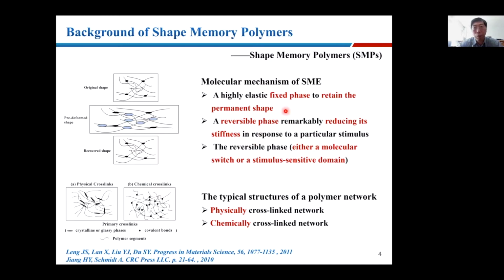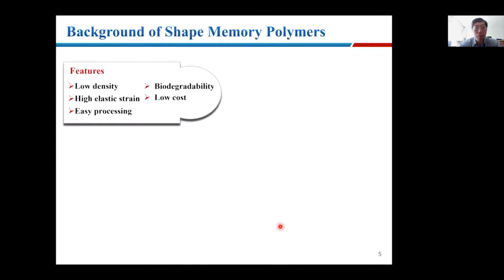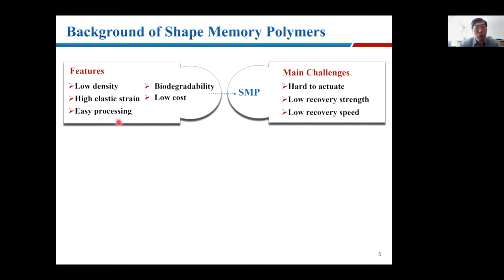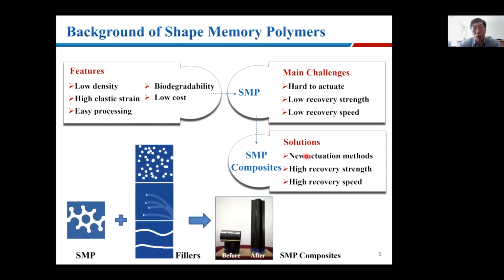So for the mechanism, for shape memory polymer, normally including fixed phase and reversible phase. The fixed phase can retain the permanent shape, and the reversible phase, that means they can reduce the stiffness in response to different stimulus. For the typical structure of a polymer network, that will include physical cross-link network and chemical cross-link network. Shape memory polymers have some advantages, like low density, biodegradability, low cost, and easy processing. But the main challenge is how to actuate, and also the low mechanical properties, including low recovery speed and low recovery stress. The solution is to make a composite.